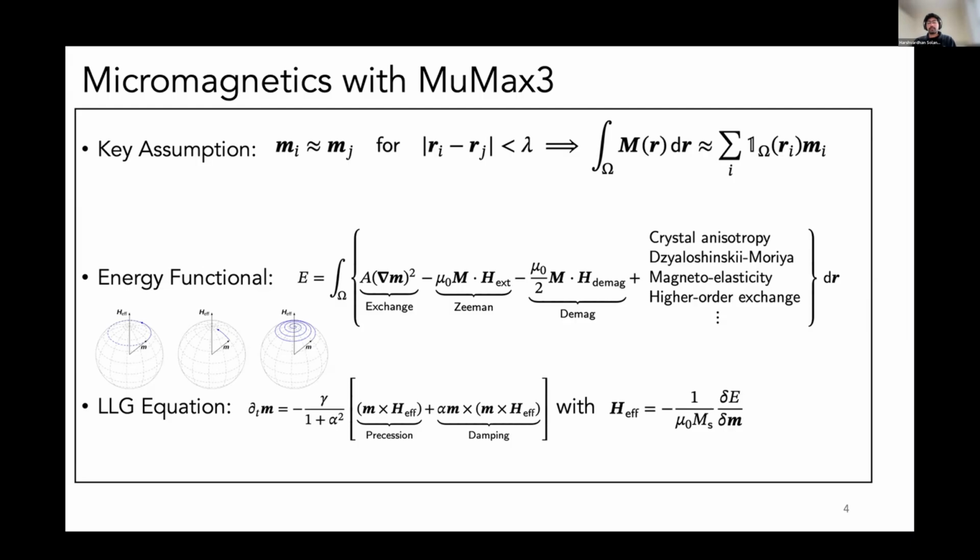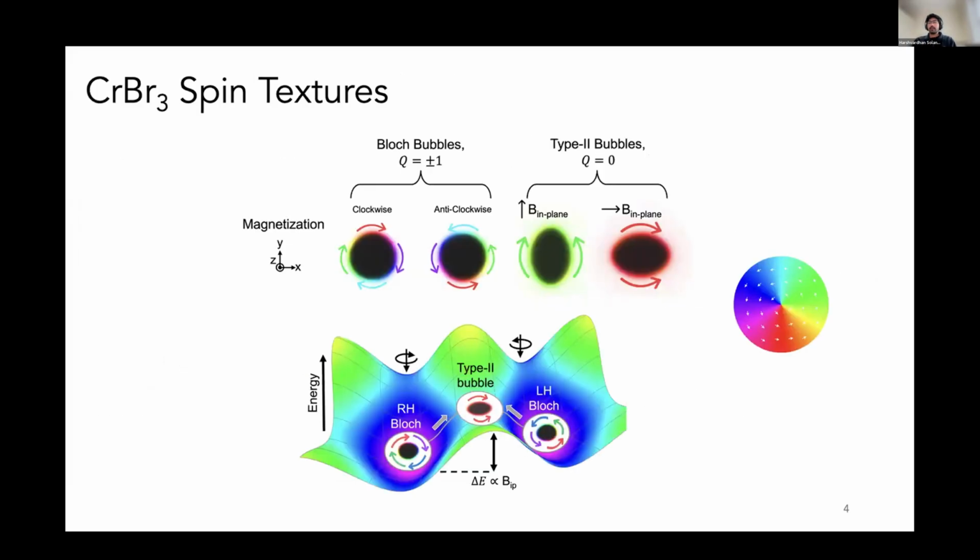And most of these simulations have been undertaken using the MuMax simulation software, which is a fast GPU-accelerated micromagnetic simulation software developed at Ghent University. These skyrmion ground states were generally obtained by relaxing under high damping under an out-of-plane magnetic field of around 50 millitesla in this case.